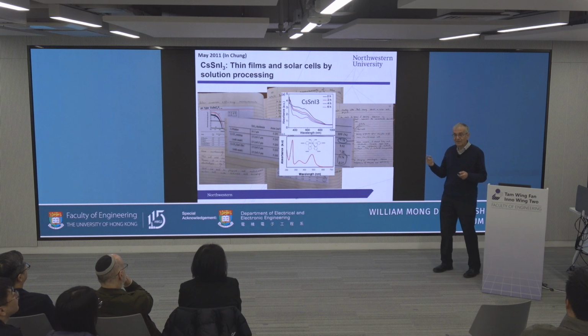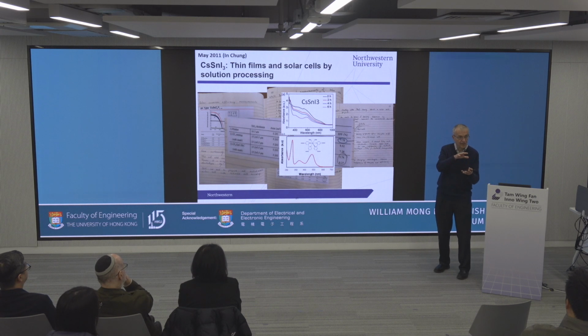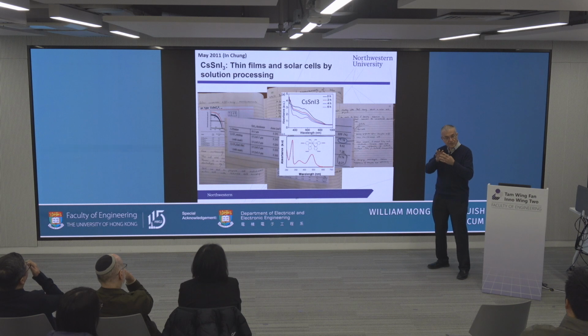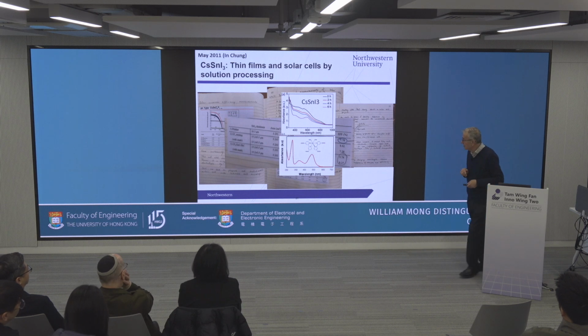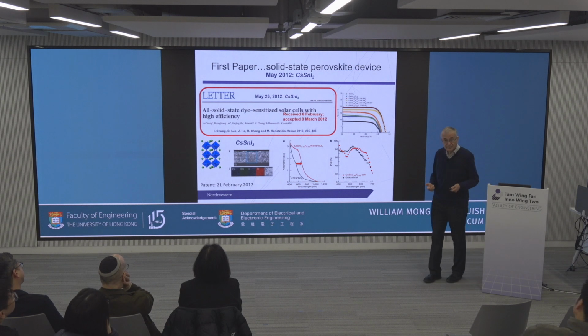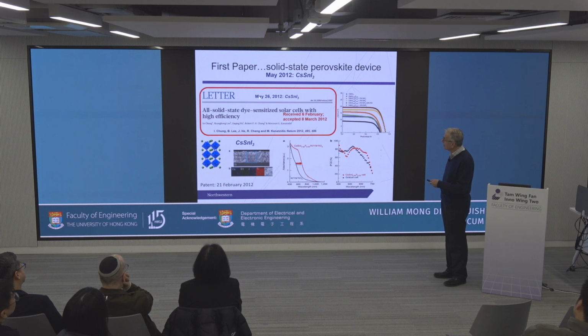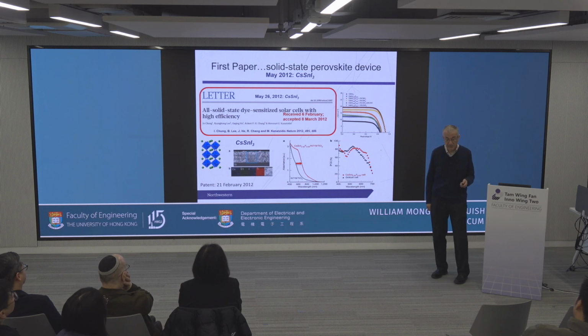Remember, we can have it both ways because near the TiO2 is actually good. It's a semiconductor. But as it goes up during fabrication, it gets a little bit doped. It becomes P-type, and that's where the electrode is. So it's doing both jobs. And therefore, we wrote it up, and we published this paper. And this came out on May 26, 2012. This is the first paper of a perovskite solid-state solar cell that was published.